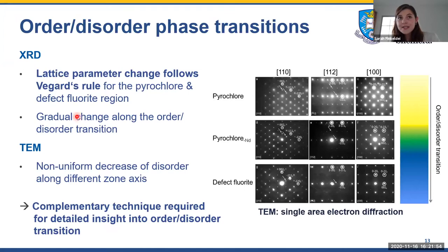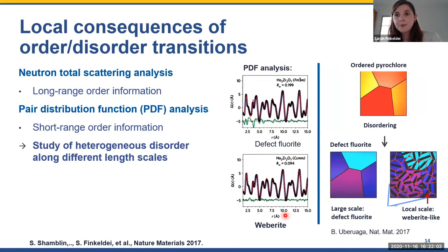So after these results from TEM, we were interested in studying this with a complementary technique. And what we did is we teamed up with the University of Tennessee, Knoxville, with the group of Professor Mike Lang. And we performed neutron total scattering analysis at the Spallation Neutron Source at the Oak Ridge National Laboratory. The neutron total scattering analysis gives us long-range order information about our material. And we also performed pair distribution function analysis.